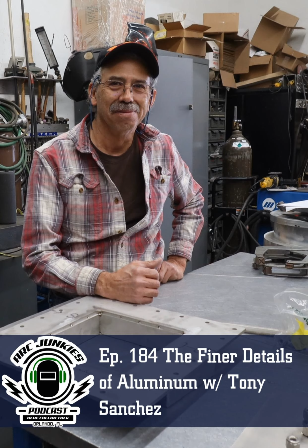Now, if you go into stainlesses and steels and everything, and you run a concave, you get rid of all your undercut. Everything just fills up and it jumps together. Metals just roll into place. So now back to the aluminum. You pushing that concave puddle, what's going to happen is you're pushing them gas pockets out. And here's another saying I have: with aluminum, you add no rod before it's time. If you want to push them pinholes out, you get it to that point and it's convexed, and then all of a sudden it drops that concave and you slip one small drop in there and you'll watch that puddle.